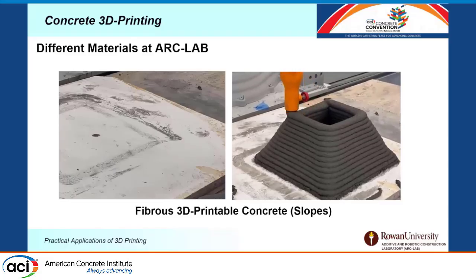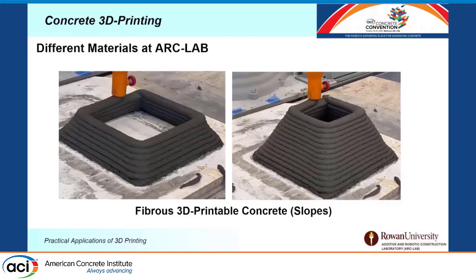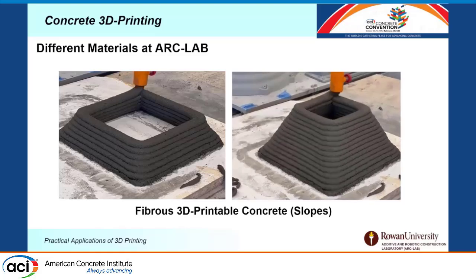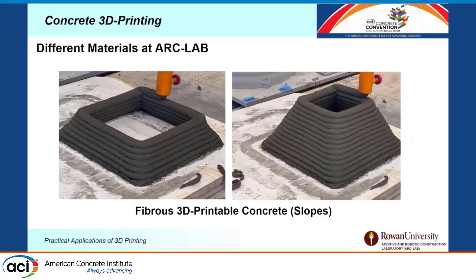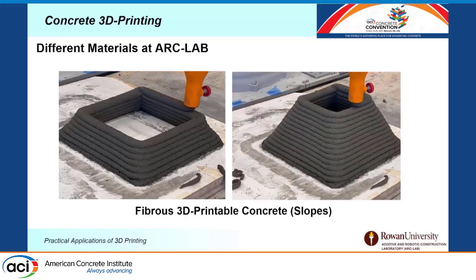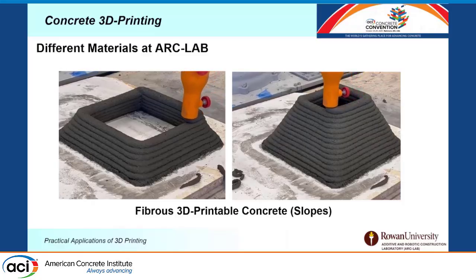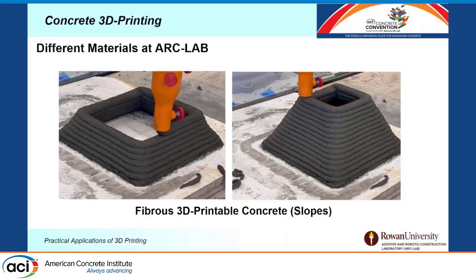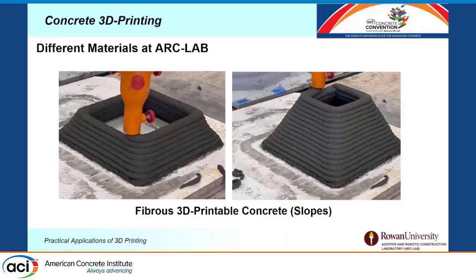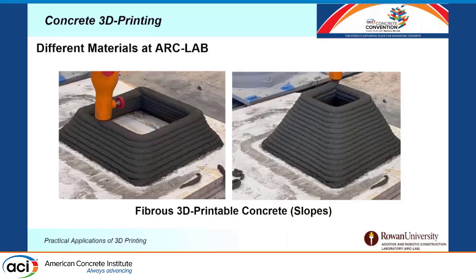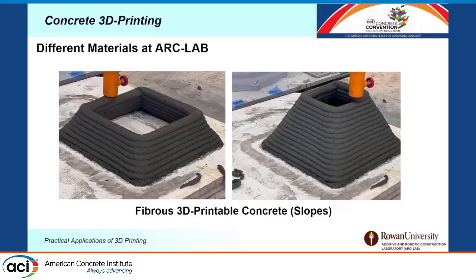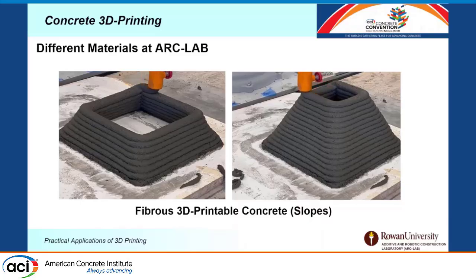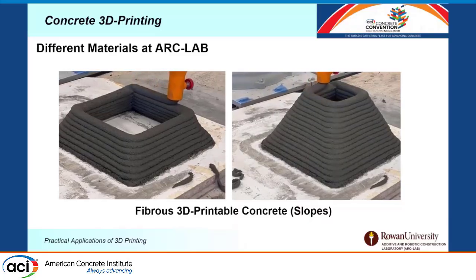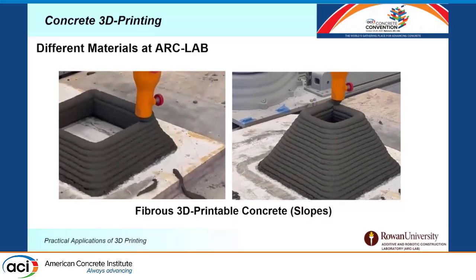As part of our material performance testing, we actually try to print on slopes. So this is a 26-degree slope from a vertical position. We printed a pyramid that is 12 inch by 12 inch by 12 inch, and the material here is using steel fibers. We also were able to print it without steel fibers.